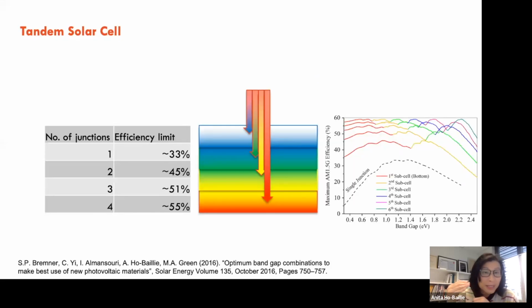So you can keep stacking cells, and you can increase it to, say, a 5-junction or 6-junction tandem, but you can see the improvement is marginal. So this graph shows the ideal band gap for, say, the 2-junction cell will be somewhere around 0.9 and then around 1.4. And then it shows the ideal band gap for the 3-junction, and the ideal band gap for the 4-junction cells.